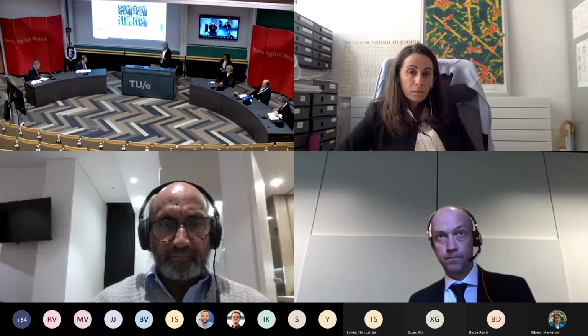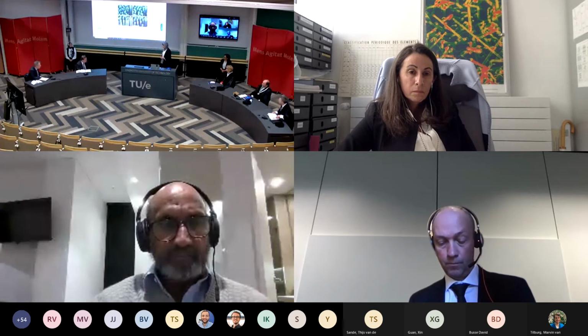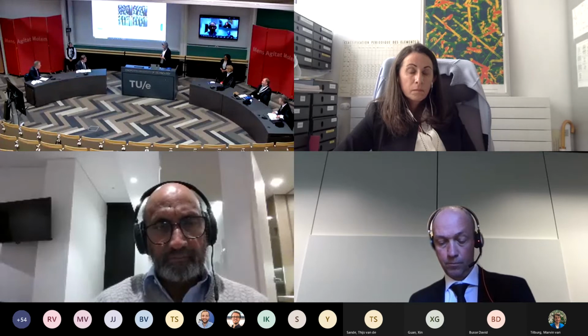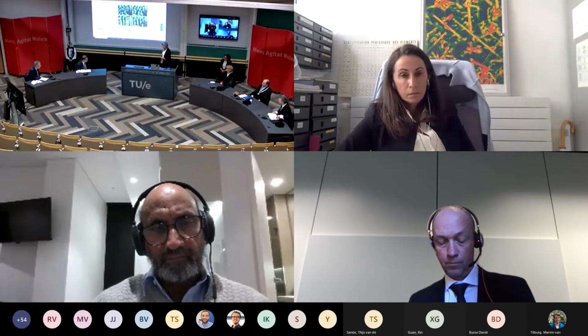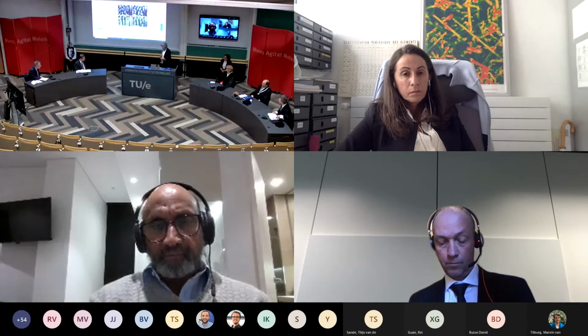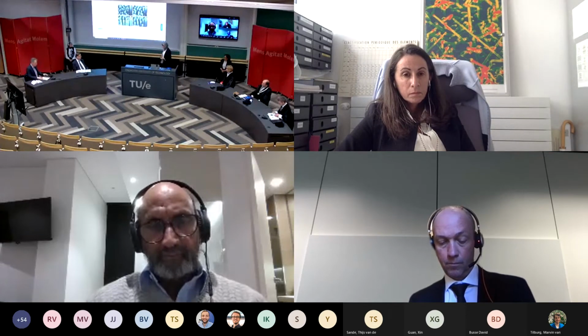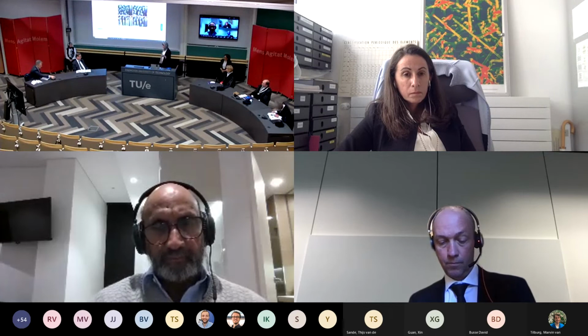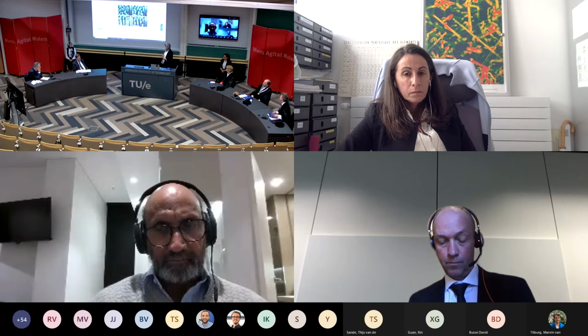Maybe a final short question. Do you think it helps to try to enhance the surface diffusion across the facet? Because that's what you do in 2D growth. Is it possible here to further enhance the diffusion of atoms? Yes, this is one of the mechanisms that we are already working on to combat, which is one of the formation mechanisms of these I3 defects. If we have limited or slow diffusion of atoms, then we enhance the density of the defects. So if we control the mobility of atoms, we can get rid of it. And of course, if we also lower the number of defects by controlling impurities and the interface, we can also reduce the number of steps at the shell surface.